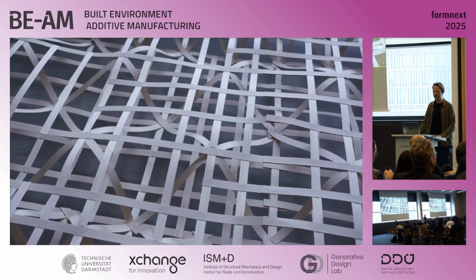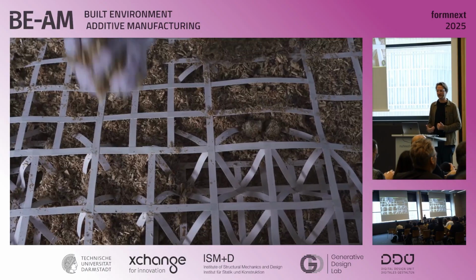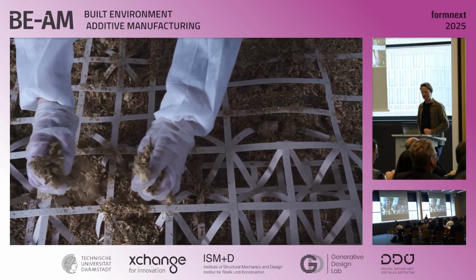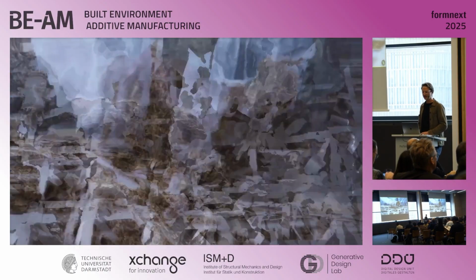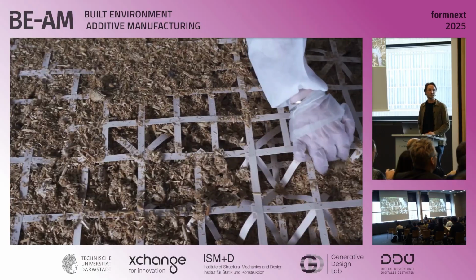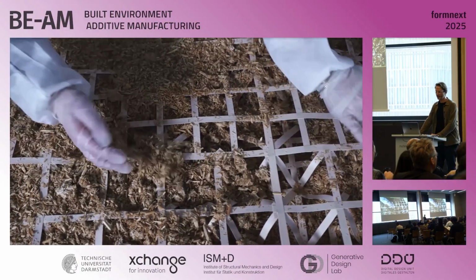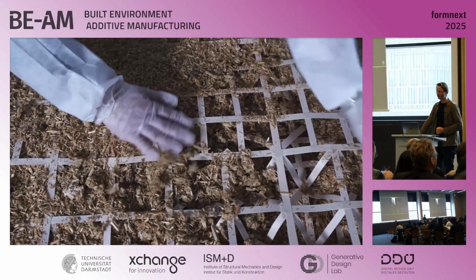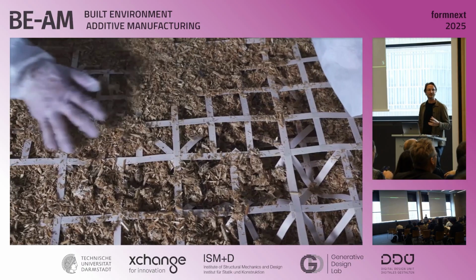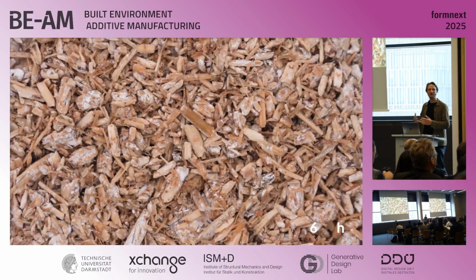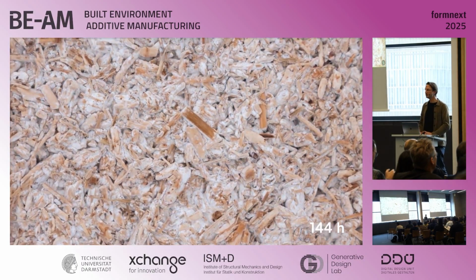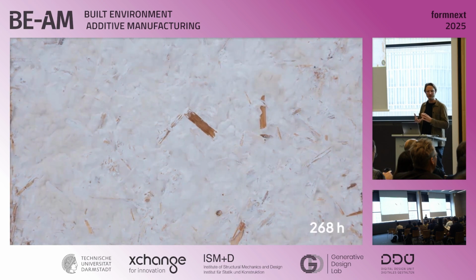In the first step, we fabricated these lattices and then filled them with mycelium substrates. Within 1 or 2 weeks of cultivation, this becomes bonded by the biogrowth, which is a bit different from concrete. We don't just pour the concrete inside; it actually grows inside, uses the lattice, and connects with the timber.